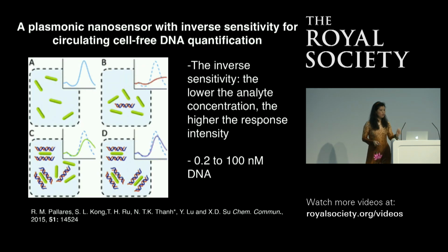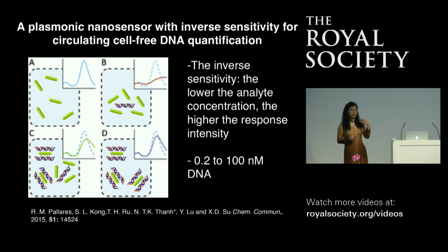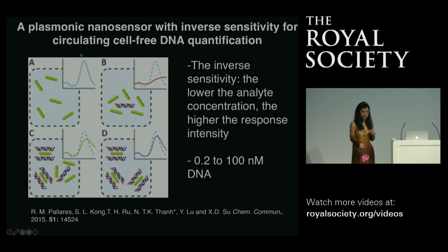And what we're going to use it for is very relevant to what Rosalind did during her time finding the structure of DNA. What she said is that the phosphate was near the outside, because we're using the phosphate backbone characteristic of DNA for the assay we are developing. So you have a gold nanorod. Very similarly to the gold sphere, you get the absorption peak there. But when they aggregate, you get the increase at a longer wavelength.